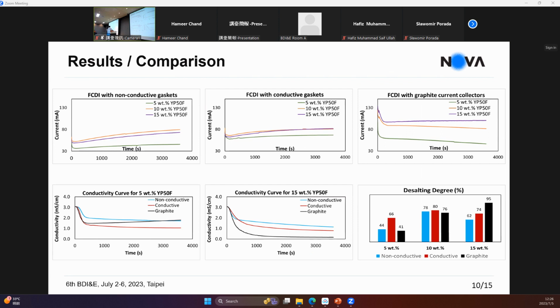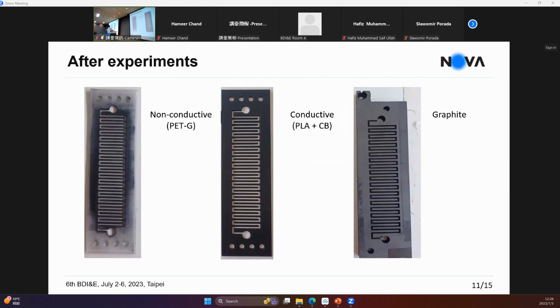What we also saw, which was quite surprising for us in the beginning, was that this current increased with time, and it increased only for the 3D printed gasket. So when we opened the stacks, what we saw was that some part of the YP50F carbon actually penetrated inside the 3D printed materials. And so we believe that it added some extra conductivity along time as the carbon penetrated into the 3D printed structure, and decreased along the time the resistance of those 3D printed gaskets.